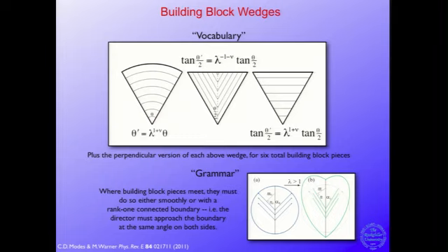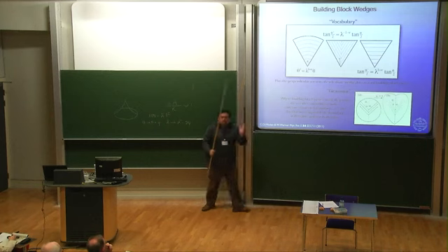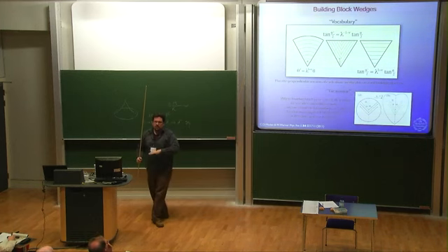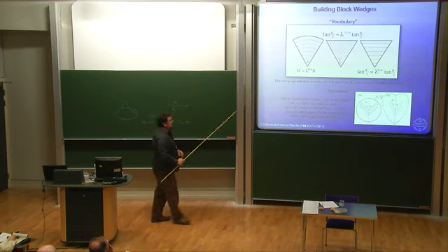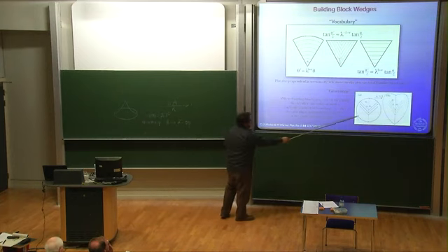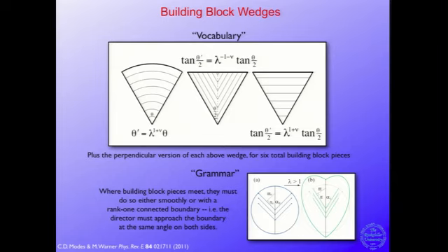So you can imagine putting this wedge onto this wedge, and then you have a smooth director field and nothing changes. Or you can imagine joining them in such a way that the angle of the director meeting the join is the same on both sides, right? And you need this because you get the length change of the projected normal direction and along the director direction at the boundary, and that length change must match, or else you get a macroscopic buildup of different lengths across the discontinuous boundary, and the material will tear itself apart, or at least be very, very stressed.